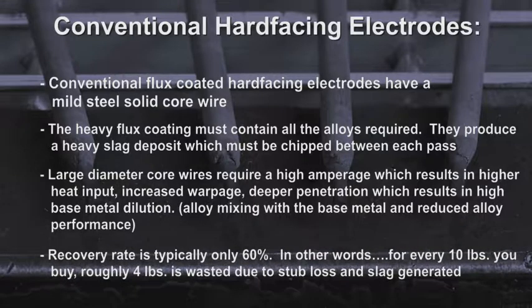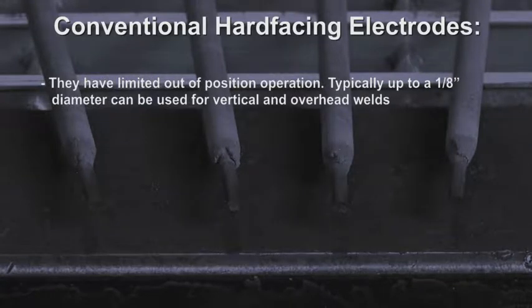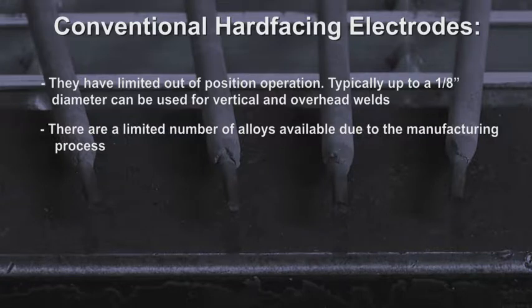Recovery rate is typically only 60%. In other words, for every 10 pounds you buy, roughly 4 pounds are wasted due to stub loss and slag generated. They have limited out-of-position operation. Typically, up to an 1/8-inch diameter can be used for vertical and overhead welds. There is a limited number of alloys available due to the manufacturing process.